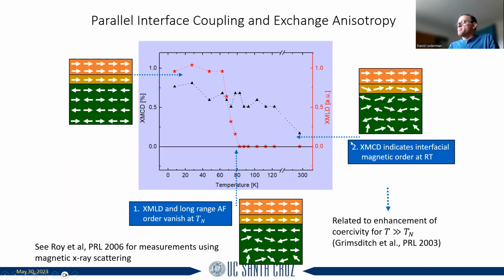Okay, so this is the picture that we came up with. The linear dichroism shows that we have long range order. It vanishes at the Néel temperature. We have interfacial magnetic order at room temperature, from the iron. So there's like a layer in here of the iron that's kind of ordering, that's tracking this thing. But then at low temperatures, this thing kind of freezes a little bit, and the whole thing shifts downwards when you look at the hysteresis loop.